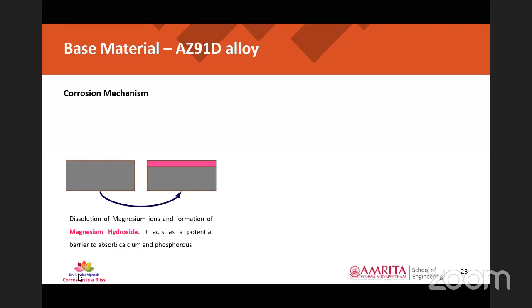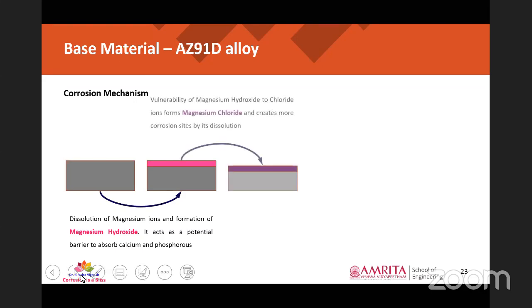So what happens is this will act as a potential barrier to absorb calcium and phosphorus. Why it is so: this magnesium hydroxide will react with chloride ions that are present in the DPBS, or Dulbecco's phosphate buffered solution, that we have created to mimic the human body environment. So the chloride ions will be attracted towards this magnesium hydroxide, and it reacts to form magnesium chloride, and this magnesium chloride just goes into solution. Why? Because it is a highly soluble salt. And after that, the magnesium has more access to phosphate ions and calcium ions.